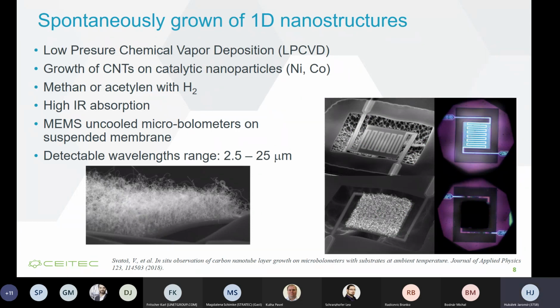Another approach is to use spontaneous growth, which can be obtained by chemical vapor deposition. Here low pressure CVD is used for growing carbon nanotubes, when catalytic nanoparticles are deposited on the substrate. As a precursor, methane or acetylene with a small amount of hydrogen is used for the growth. This film of vertically aligned carbon nanotubes has very high absorption of the infrared part of the spectrum. So we use it to cover the membrane of microbolometers, as you can see here in the pictures.